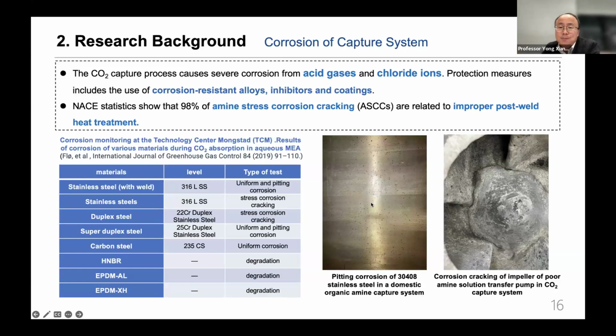And also you can see the middle pictures. We have some pitting on the stainless steel 304. It's the same for other stainless steel, the pitting can also be observed on the surface. Why does this happen? We searched for the reasons. Maybe the chloride ions in the systems accumulated with time. So when the chloride ion concentration is very high, then maybe the pitting happens. So maybe some of the stainless steel in a fresh new CO2 capture plant has no pitting problems. But with time, maybe several years later, they will have pitting problems because of the chloride ion accumulation.